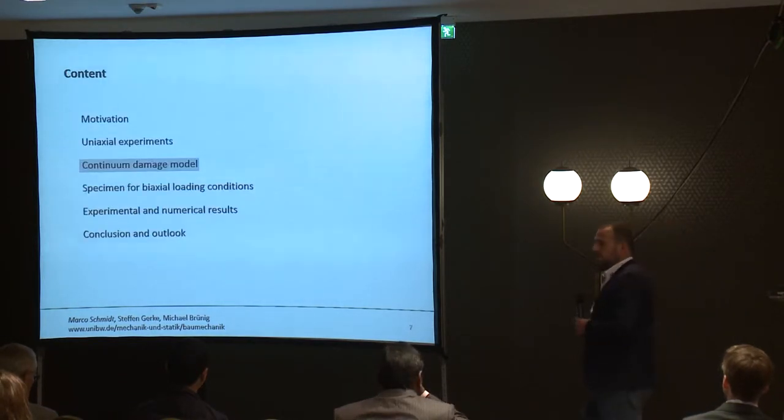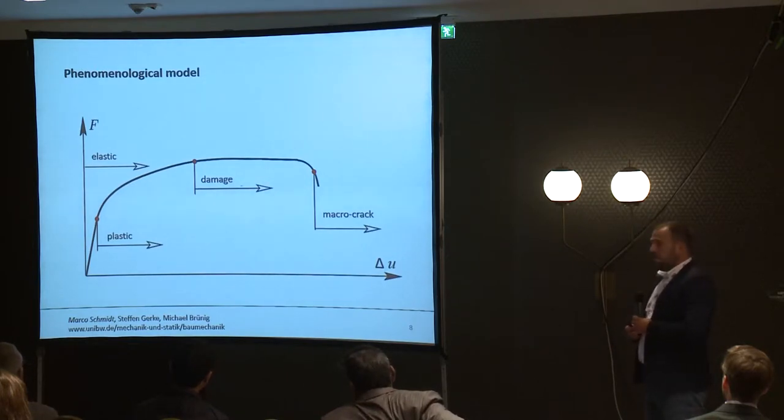Before going into biaxial experiments, let me show you some details about the continuum damage model. We have a phenomenological model, which I want to explain on the basis of a force-displacement curve. With the beginning of the load begins the elastic behavior. When a yield condition is reached, a plastic behavior, which is described by a flow rule, occurs in addition to the elastic behavior.